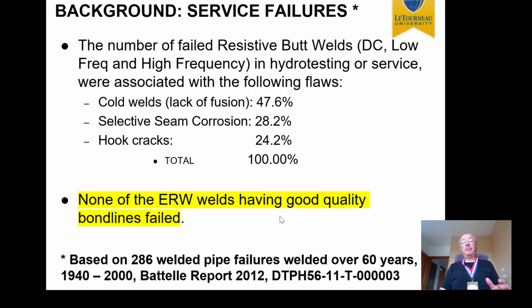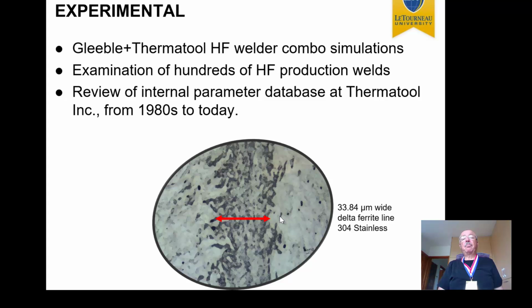Yet they have never found any weld of good quality with a good bond line that actually failed. So that's an indication that good bond lines never fail, as we observed also. And this is basically an overview of those bond lines.